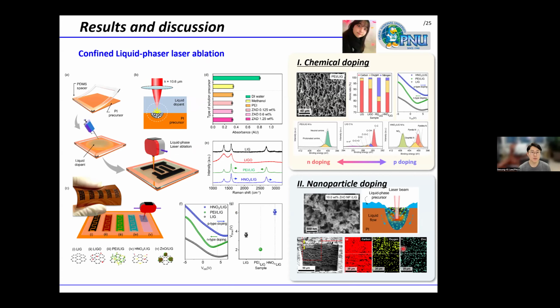In this approach, we have recently advanced the technique one step further. Specifically, we introduced laser ablation in solution to selectively functionalize porous graphene. As shown in this figure on the left, by locally positioning the dopant solution and inducing the laser, and then inducing some reaction, we can achieve selective chemical doping of porous graphene in this system. Based on composition analysis and transistor measurement, this method enables tuning of the graphene from N-type to P-type material. It means we can chemically dope the LIG using this system.